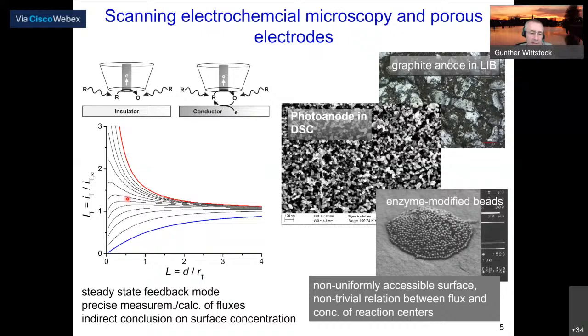That is all fine and well established for smooth surfaces. Unfortunately, many technically relevant surfaces are not smooth. I just put here a few examples from my own work, like a graphite anode in a lithium-ion battery, which is composed of particles held together by a binder. A photoanode in a dye-sensitized solar cell is composed of sintered nanoparticles of titanium dioxide, which are coated by a dye sensitizer. And in this pore space, there's an electrolyte volume.